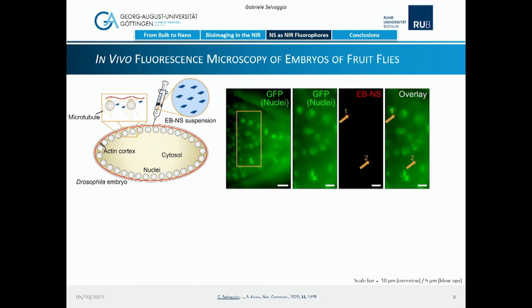And here, in this black box, you apparently see nothing, and you probably really don't see anything because of the beamer, but you have to believe me, there are 2 red spots here, which are the nanosheets of Egyptian blue. And that's one of the main advantages of working in the near-infrared, that you get low to none autofluorescence, therefore very high contrast when you do bioimaging.